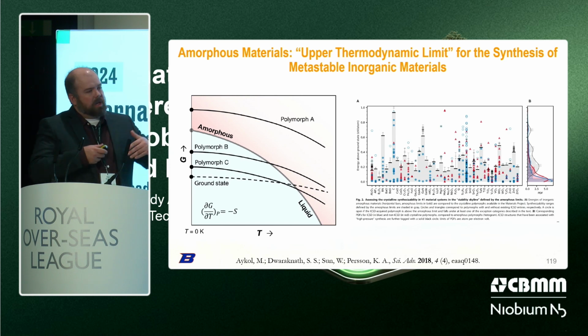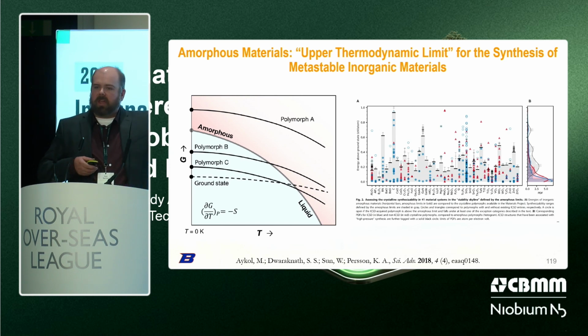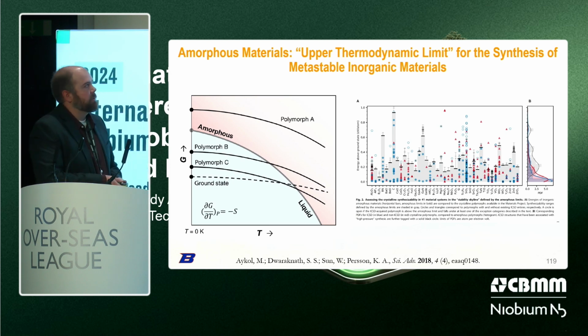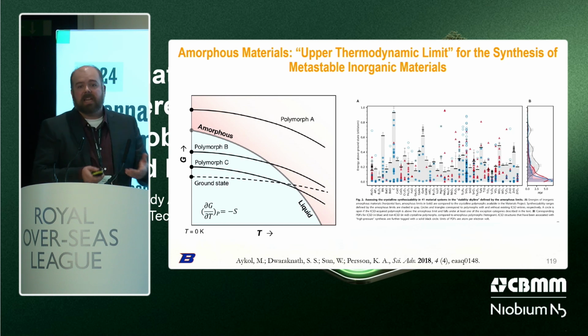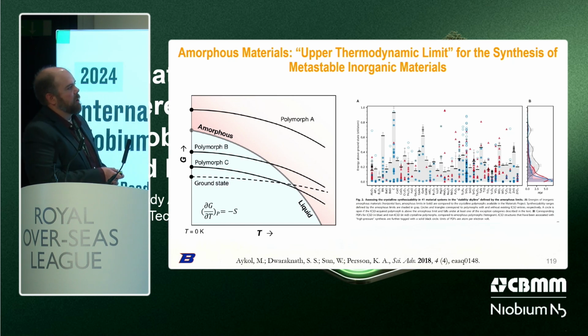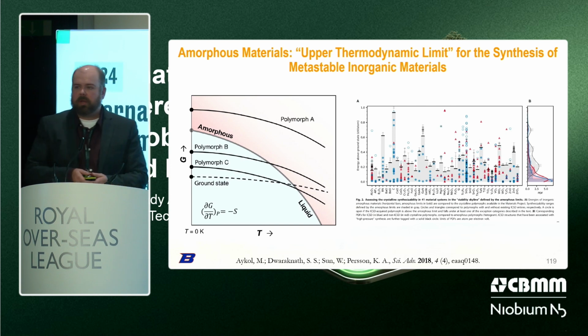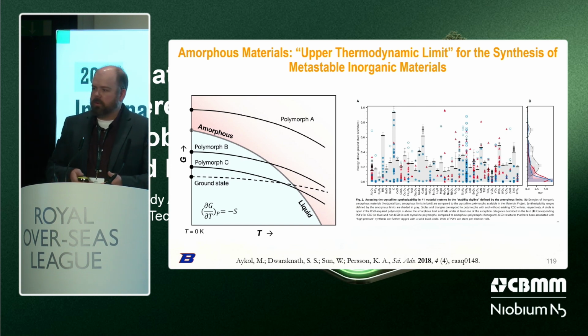And so you can associate that amorphous material with one of the upper limits, you could say a threshold, for a metastable inorganic material to exist, right? If you exist at these black bars, essentially anything below them are states which we could get to, but may not be obtainable through normal conventional ways of just heating them.